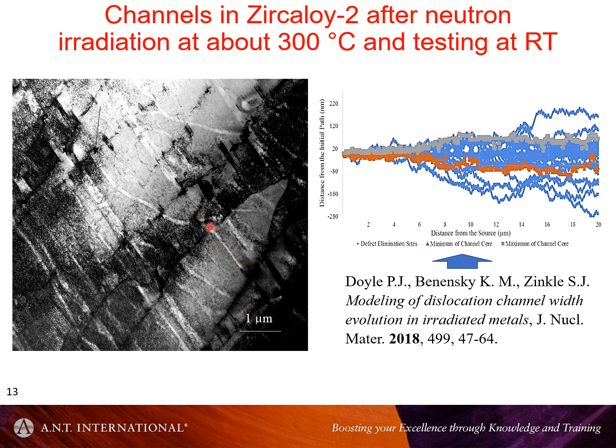It's possible to deform in these softer regions more than anywhere else, and the fact that it's a lower volume, even though you've got a high strain in this narrower volume, the macroscopic strain may be quite low, but the microscopic strain in the channel is actually quite high. So this is actually a manifestation of some reduction in the ductility, and a lot of these ductility drops that we see associated with the high strength are primarily related to this feature in zirconium alloys.